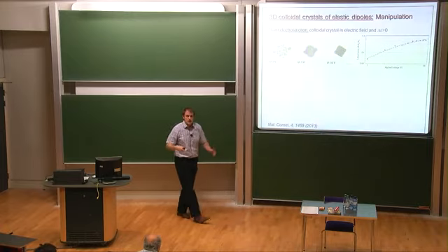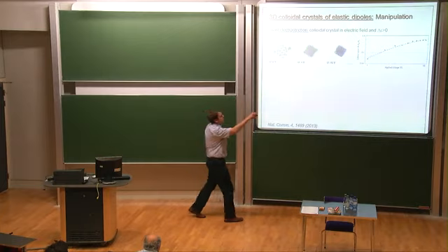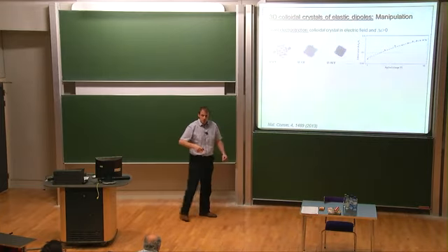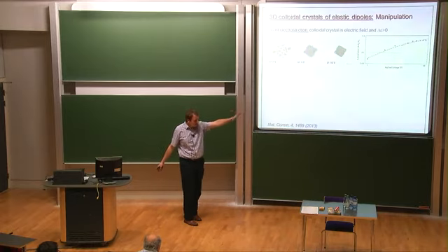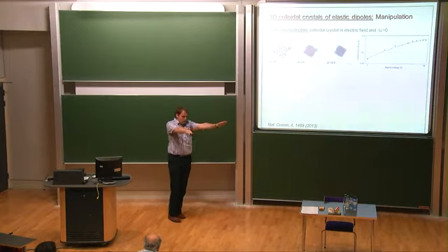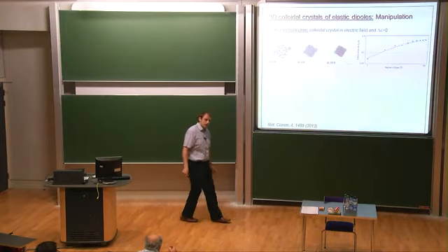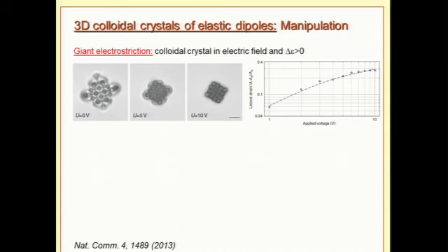This is a large change in the lattice constant, but there's an important condition: this works only if the dielectric anisotropy of the material is positive. That means the director wants to align along the field direction. This is positive dielectric anisotropy. And I'm sure I don't need to remind you that changing the lattice constant will directly affect light transmittance, photonic bands, anything in this kind of structure.